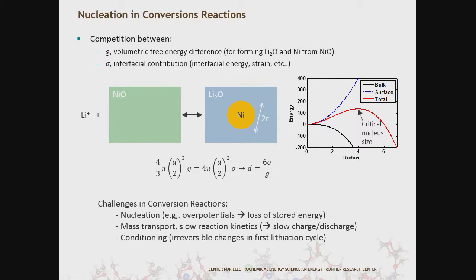So the general idea, one of the reasons for this overpotential is the fact that when you're lithiating, let's say, nickel oxide, you're forming nickel nanoparticles in a lithium matrix. This has to do with forming a critical nucleus, so you're creating surface area in this process. That new surface area has an energetic cost, and that leads to typically a sort of classic idea of critical nuclei.